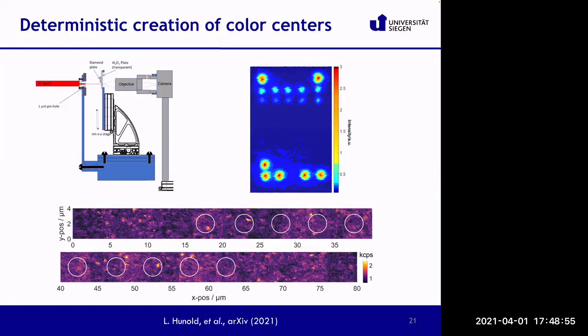For nitrogen vacancy, this has been done by laser irradiation. Essentially you have a laser that hits a sample, and by hitting locally, you create the nitrogen vacancy. Unfortunately, this is not yet possible for the silicon vacancy. So some people use the focused ion beam to create localized implantation. On the other hand, the focused ion beam has a very low energy, so it gives you some additional limitations. In our case, we used much higher energies, so we have much more flexibility, and we adopted a 1 micrometer pinhole in order to select the area in which we want to do the implantation.